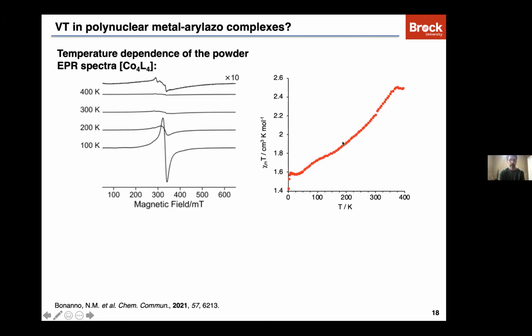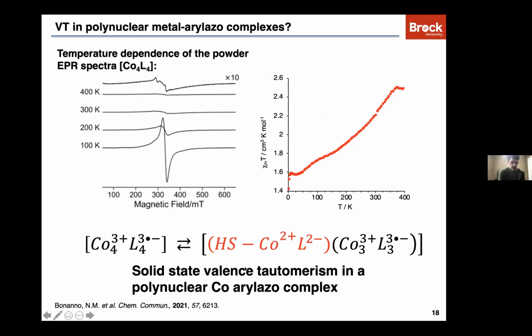So this is the SQUID data. Again, low temperatures consistent with coordinated radicals. At high temperature, we have a higher value of chi-T, which is consistent with this equilibrium, where we have 1 cobalt 2+ and 1 ligand dianion. So in this complex, we have a single electron transfer. So there's only 1 electron transferring from ligand to metal.